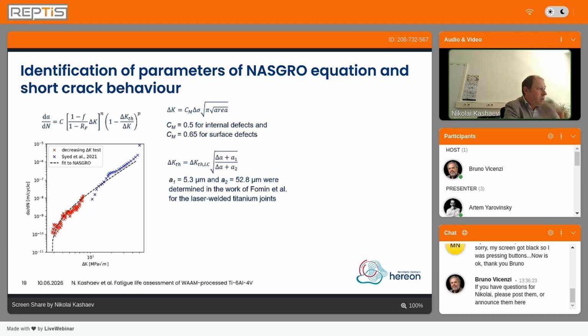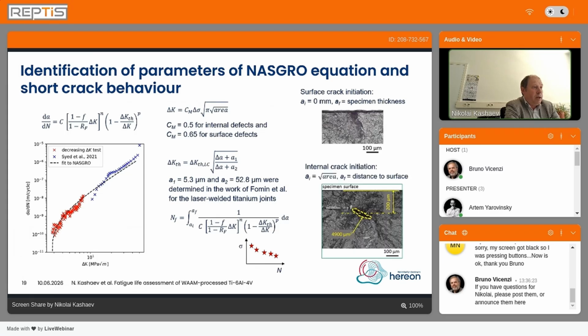Here is written how we can do it, and we identified also our cyclic curve. Here we used a little bit more modified equation describing the cyclic curve using the El Haddad equation. And then, in principle, in a similar way, we can predict each point on the S-N curve. Here are the surface initiation, and it is possible also to consider complex defect sizes, for example, using the Murakami approach. If we consider the area of the defects, then we can also consider the equal area with regard to the equivalent crack lengths for this area.